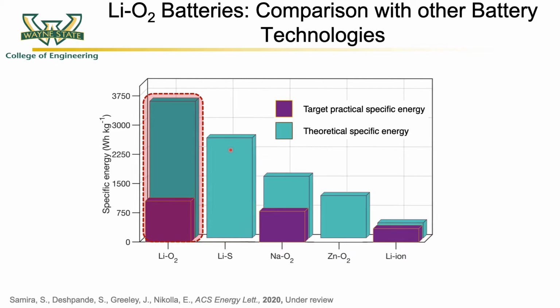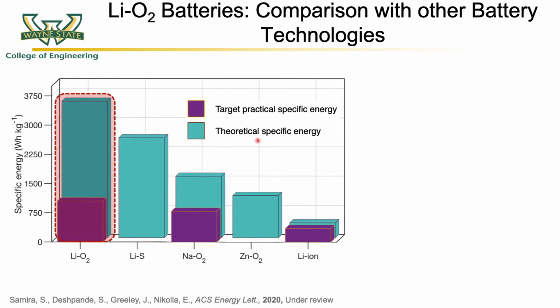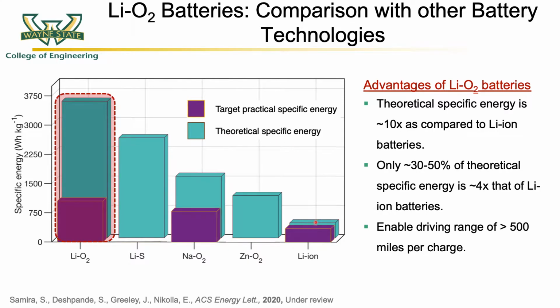Lithium oxygen batteries provide a tenfold enhancement in the theoretical specific energy as compared to that of lithium ion batteries. In addition, achieving roughly 30 to 50% of this theoretical specific energy would result in a fourfold enhancement as compared to lithium ion batteries. This target practical specific energy is close to that of gasoline, thus enabling potential commercial realization of these technologies, which can enable a driving range of more than 500 miles per charge.